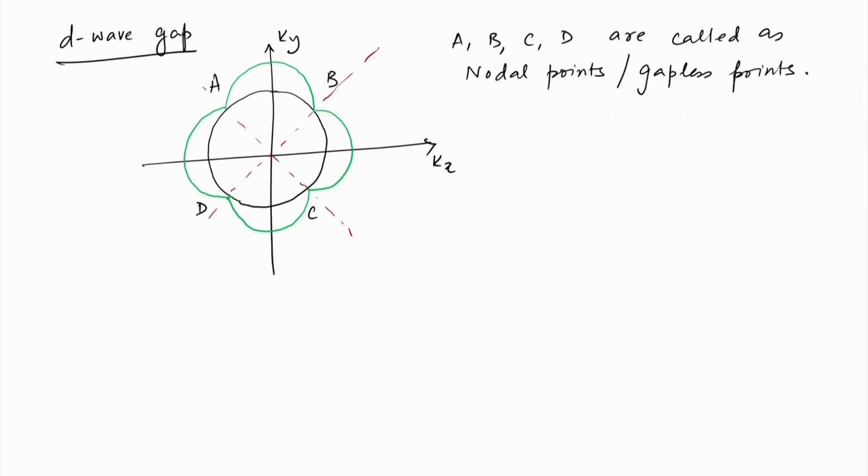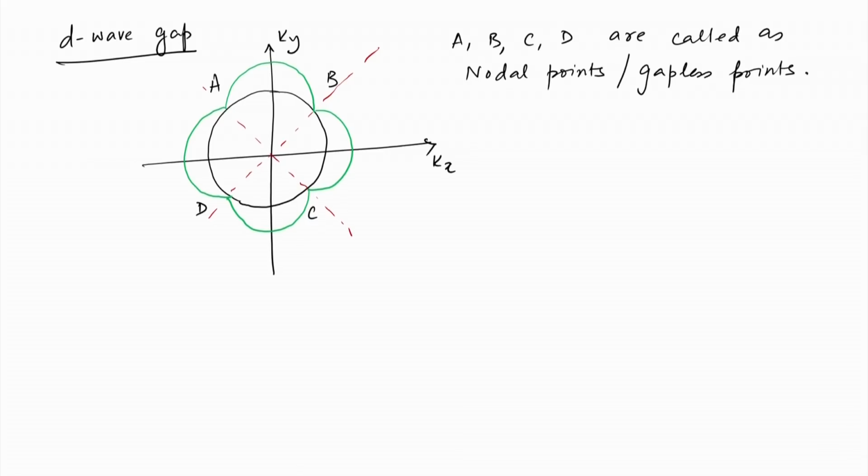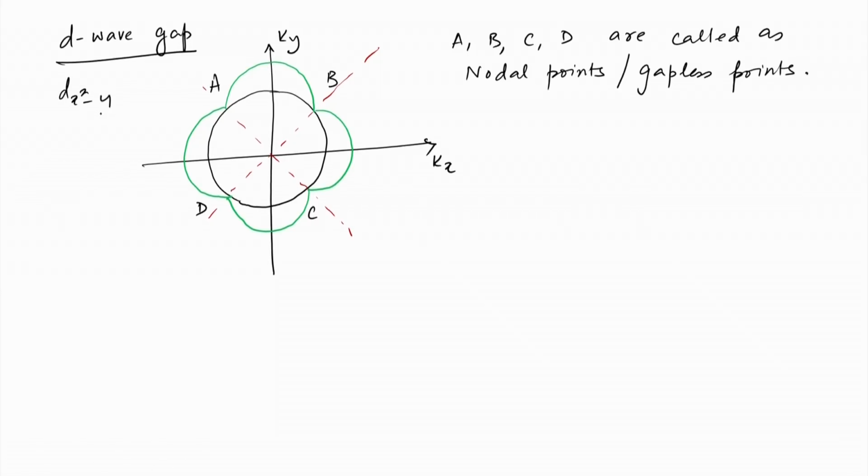So, if this is the structure of the order parameter in an unconventional superconductor, in the conventional superconductor of course, we have seen that the gap is isotropic in any direction, but suppose the gap has such a symmetry, then what are the things that we expect. And of course, as you can see, the other ones, dxz, dyz, xy etcetera, and d 3z square minus r square, are more complicated. These other things have gaps around different directions, but by and large this explains how the dx square minus y square gap looks like. So, it has a k dependence.